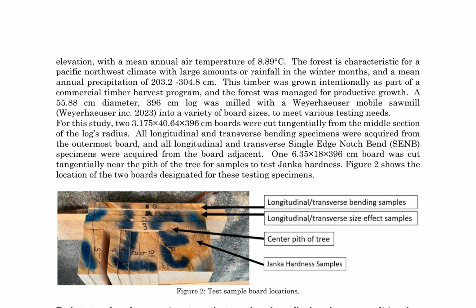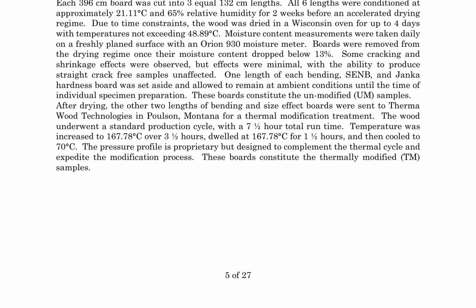Subsequently, the boards underwent an accelerated drying regime in a Wisconsin oven for up to 4 days, with temperatures not exceeding 48.89 degrees Celsius. Daily moisture content measurements were taken on a freshly planed surface with an Orion 930 moisture meter, and boards were removed from the drying regime when their moisture content dropped below 13%. Minimal cracking and shrinkage effects were observed, allowing for the production of straight, crack-free samples.